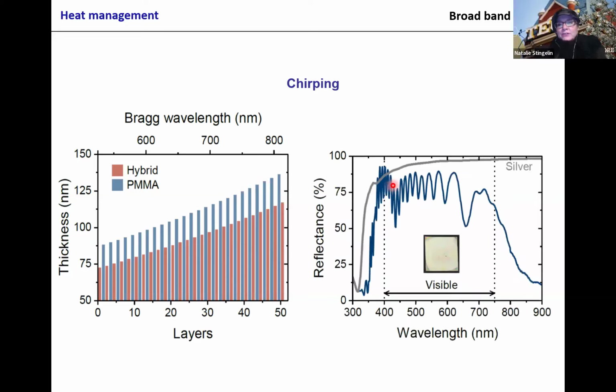And when you do that, you get a plastic that in the visible looks like silver. Here you have the reflectance, and just out of plastics, you get something that really behaves like a silver layer. This is also shown here: if you get more and more layers, you see it in the absorption.